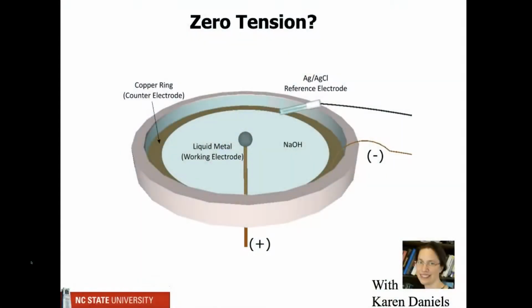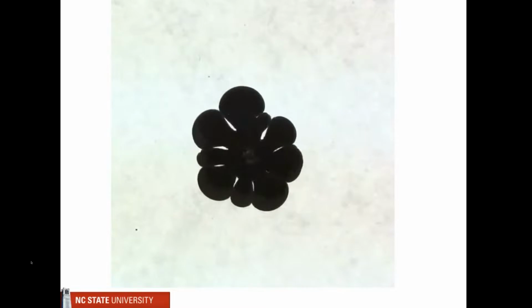So the way we did this with Karen is we made a little swimming pool. It's about this big. It's more like a petri dish. And we attached an electrode to this little droplet, and we apply the voltage, and we look from the top down. And so this is what it looks like. And so here it goes. It's spreading like a pancake. But not only is it just spreading and spreading, but it's actually forming fractals.